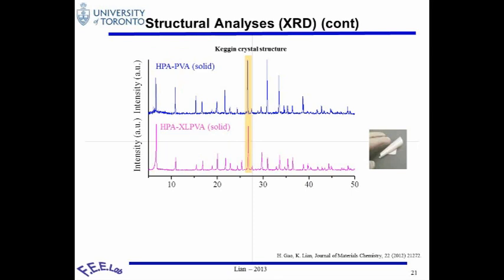So these are the three peaks that we can use for comparison, so that my student did a really detailed work looking at the TGA, how much water you have, and then basically look at the ratio of this peak versus the hydration peak with the Keggin peak, which is a fixed peak, or looking at the dehydration peak with that peak. So we can generate a working curve to know exactly how much water based on XRD, based on the conductivity, so that we can have a very good idea.